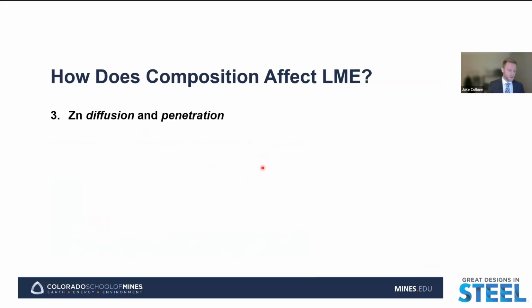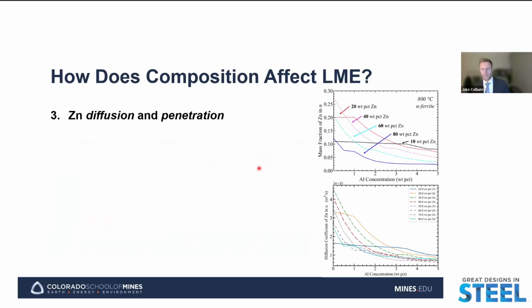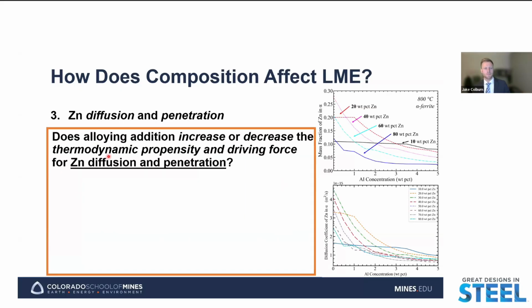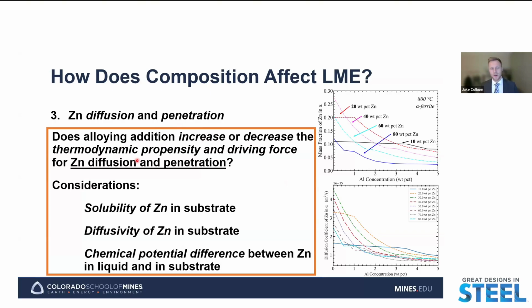And then taking a look at zinc diffusion and penetration. Again, the main question that we could ask here is, how does that alloying addition increase or decrease the thermodynamic propensity and driving force for zinc penetration and diffusion? So basically, as we add that alloying element, are we going to increase or decrease the driving force for zinc to diffuse and penetrate into the substrate, that being, again, detrimental to LME susceptibility?